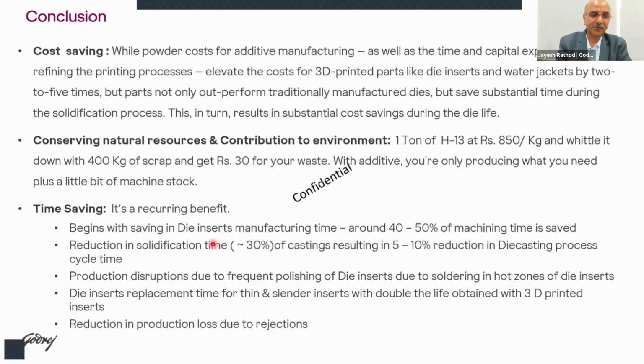With respect to time, the process is quite faster. If you want to achieve some profile by the conventional method versus 3D printing, the total lead time for making an insert has an advantage of about 50%. So that is one advantage. Then during operation, there is a reduction in solidification time of around 30%, and a 5 to 10% reduction in die casting process cycle time. This is a great advantage to the foundry when they are using the tools which are made by using 3D